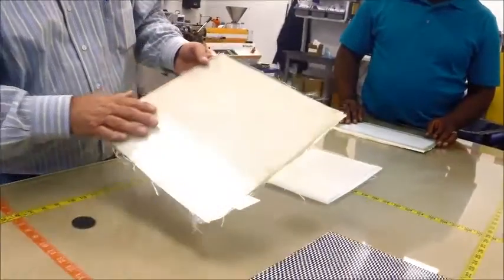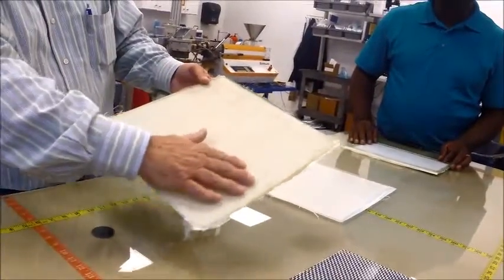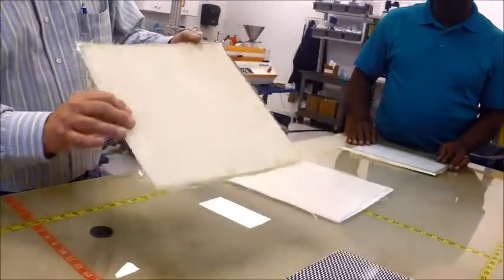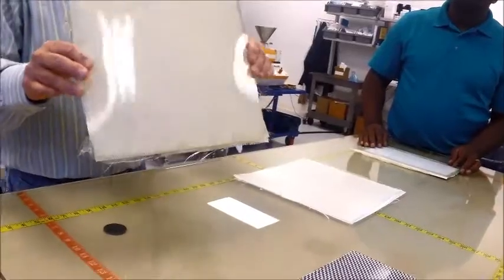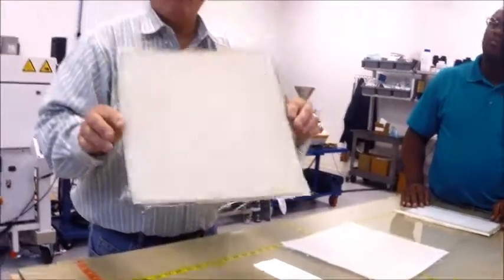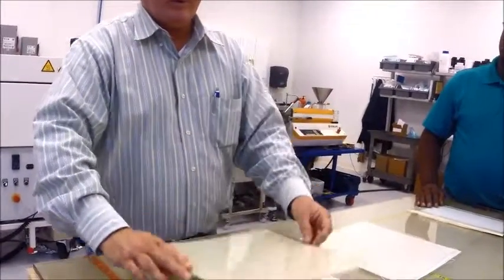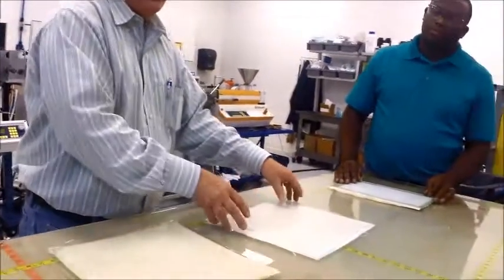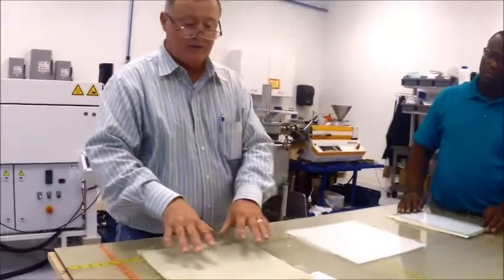As you can see, our surface is absolutely 100% porosity and void free, showing that you can make an Innegra laminate with either a vinyl ester or an epoxy resin and achieve outstanding results.